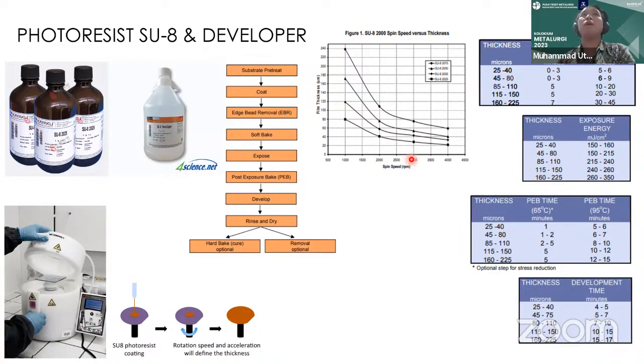So say if I want to get a 50 microns thick film, I can try to spin an SU8 2050 at 3000 RPM to get a 50 microns film thickness. And then based on the thickness of the films, I should bake the SU8 on the silicon wafer for these temperatures and time. And then after I do the soft baking, I expose the SU8 using UV lights. So I put a mask over the SU8, and then I expose the SU8 over the mask using this specific energy